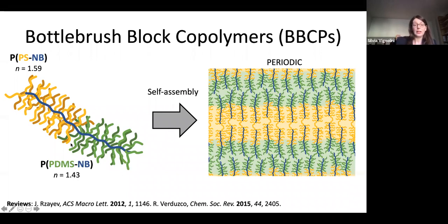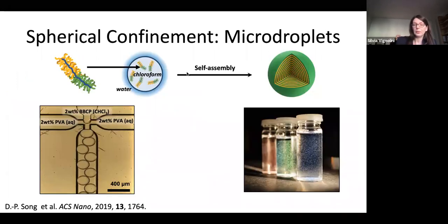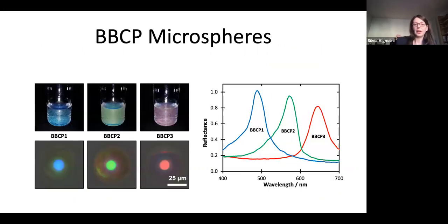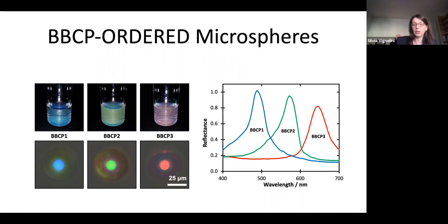But they are also a really interesting system, because, similarly to the cellulose nanocrystals, they self-assemble into a layered structure, and they have the right scale to be on the wavelength of light. If you use the same trick of assembling them in a confined geometry, you can similarly obtain nicely colored pigments. The big advantage now, since you have a polymeric system instead of a colloidal system, is the processability of the method, which is really fast. You can obtain this mixture in really 5 minutes of self-assembly time, while the cellulose takes a little bit longer, a few hours, to get the same level of intensity. And then you can again get color in the entire visible range that are really bright and interesting.